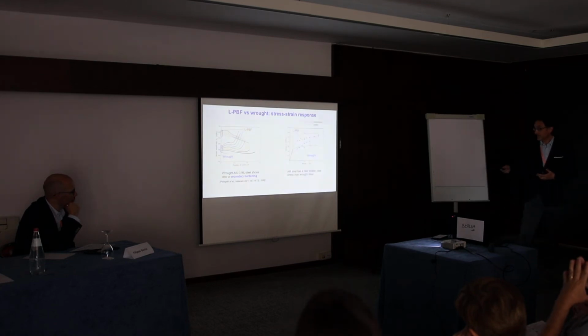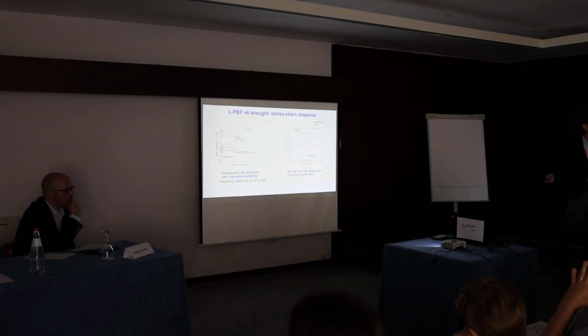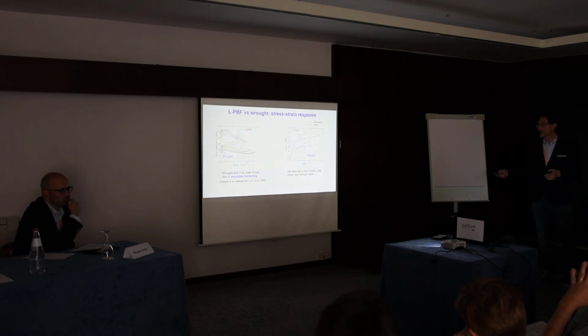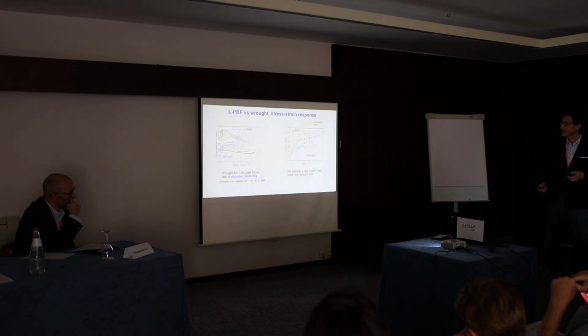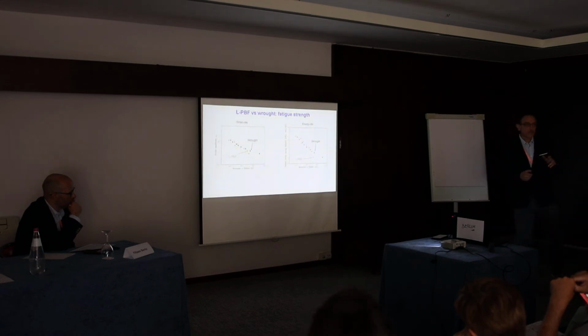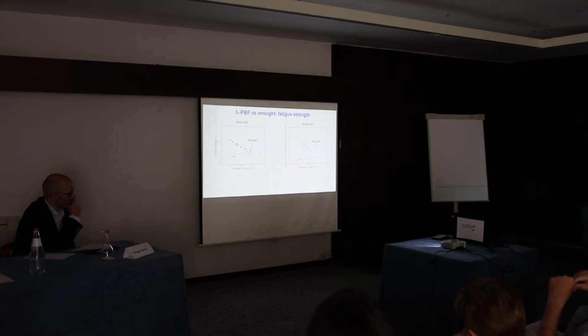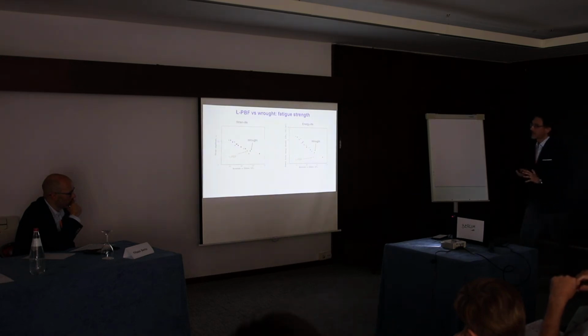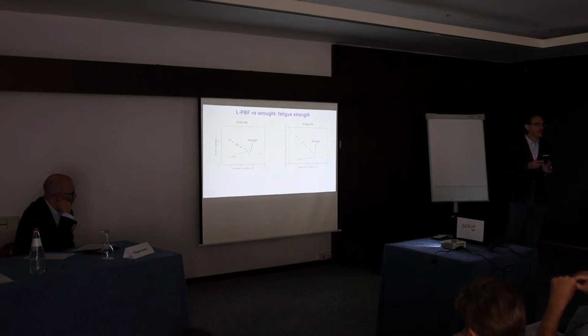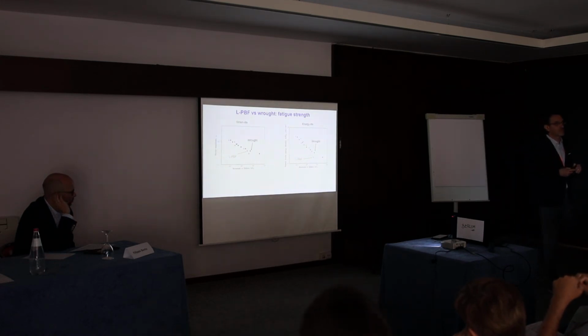For this reason, if we compare the monotonic and cyclic curves, you can see that, of course, as I told you, the additive manufactured material shows a very clear softening behavior. On the other hand, the raw material shows a very pronounced hardening behavior. But it is interesting to note that despite this very different cyclic plasticity behavior, at first sight, the fatigue-like behavior seems pretty close or similar, let me say.